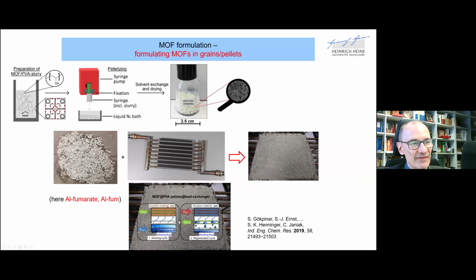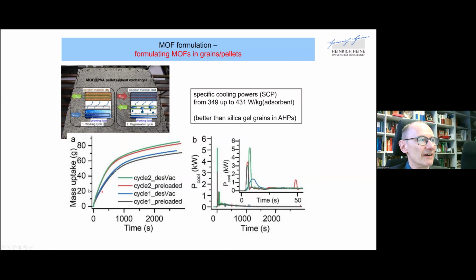And then this was investigated in terms of its water uptake and release and its capacity. And that is shown here. So mass uptake in terms of water over time is rather quick. And then the cooling power, which is about 350 to 400 watts per kilogram of adsorbent. So it is only the kilogram of MOF in this case. It's not the whole heat exchanger.